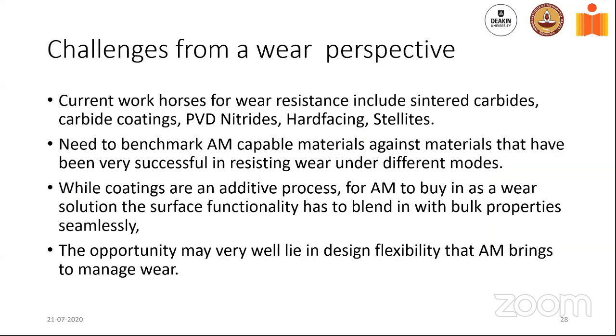So what are the challenges from a wear perspective? Going back to additive and the whole aspect of solving wear, we have current workhorses, and I talked about that. We need to benchmark additive manufacturing capable materials against what's been successful in resisting wear in different modes. I would really start with stellite, tool steels, and white cast irons. I will not go to high volume fraction tungsten carbide cobalt to be additively manufactured; I think that would be much harder. But when you look at metallic materials, which are workhorses for wear resistance under many conditions, those are the materials I would look at for additive manufacturing to solve specific issues.